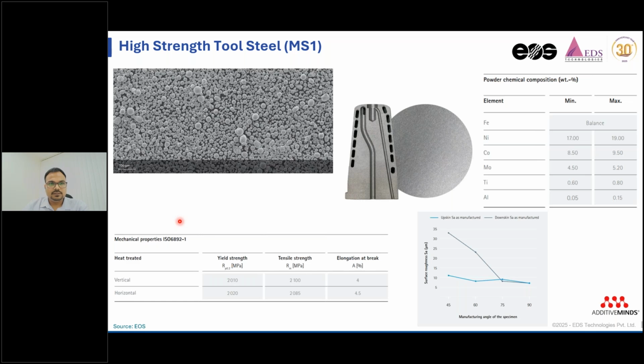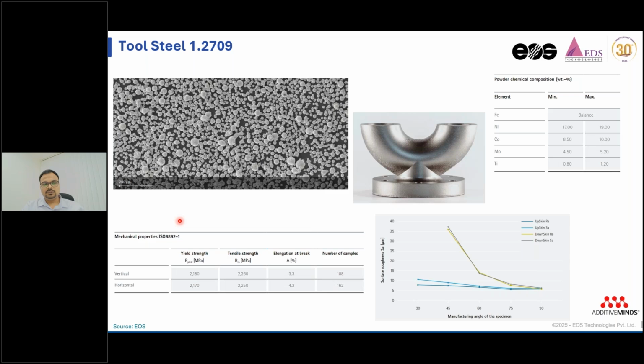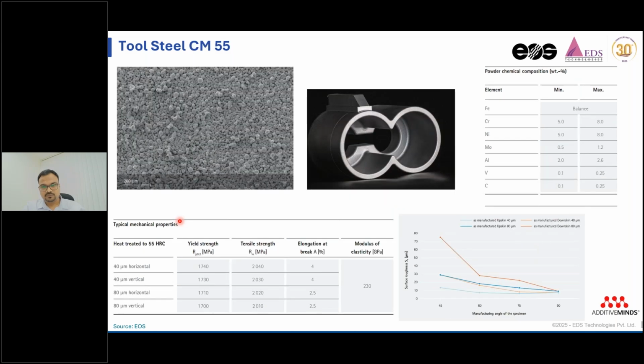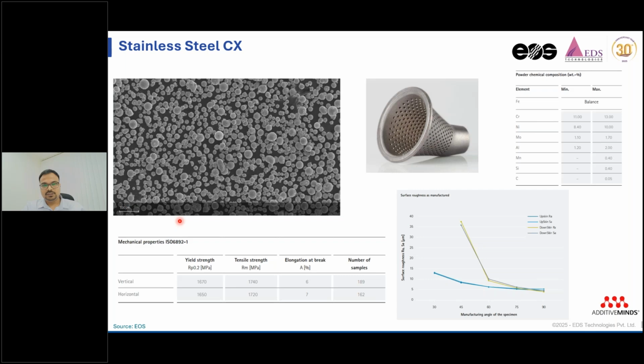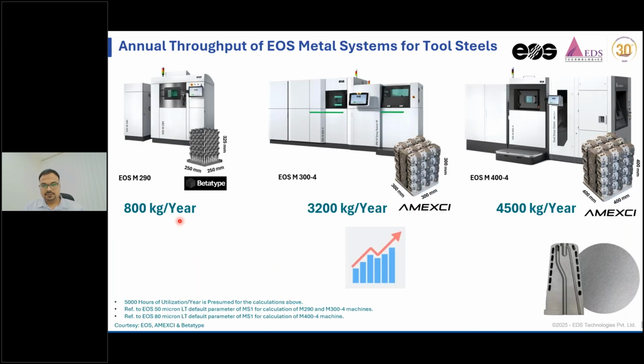So talking about materials, the highlight is that we have high strength materials which can directly cater to your tooling requirement, whether you want to replace your injection molding tool. We have maraging steel, which is a martensitic aged alloy. It is a high strength material, and you can calibrate the hardness as per your need. Then we have tool steel 1.2709, which can print your tool directly. We have CM55. We have stainless steel tooling material also. And over the year, you can again imagine the tons of steel being produced for your day-to-day tooling application. So you don't have to print the entire tooling with 3D printing, but only the areas which have criticality in terms of cooling.